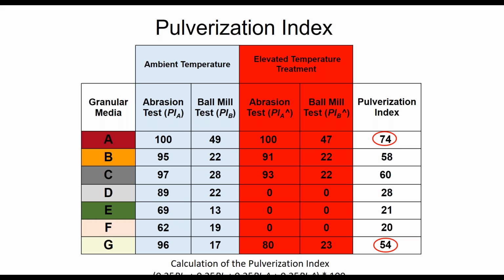But what we are seeing, certainly as we look at system A, the system that we are dealing with in terms of a ceramic media, it is superior. The higher number of the pulverization indexes is more resistant to that breakdown. And then system G is a silica sand. The other thing that we'd like you to glean from this slide is the mechanism of breakdown does not always act the same. Certainly, we see the ceramic media as superior in terms of its abrasion and wear resistance, especially at elevated temperature. But if we could reduce the amount of impact in treating sand systems in the foundry, mold, melt, and fill, we'll also have greater life of our granular media.